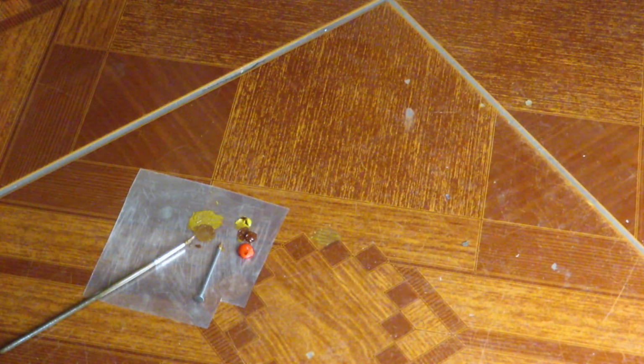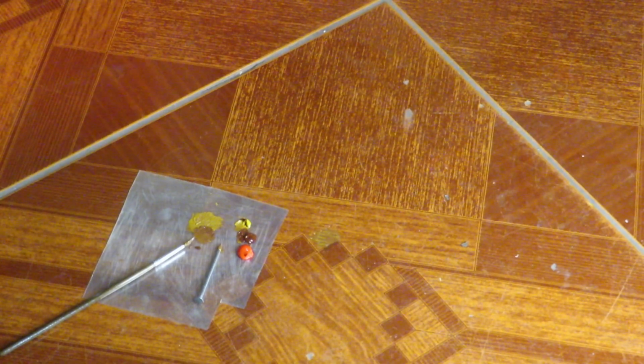This method is not very good though in places with some traffic. If you look at these tiles where the enamel is fire hardened into the ceramic, you'll notice regular traffic has removed most of the surface colors, the pattern. That is what will happen with any painted coat, and much faster than a fire hardened one. So this method should be used in places with no traffic. In this place, it will be a good method.